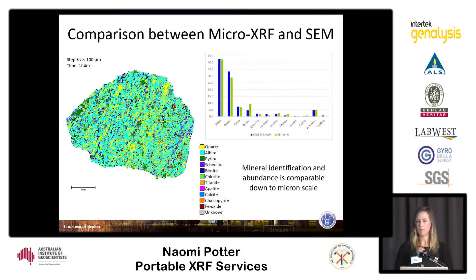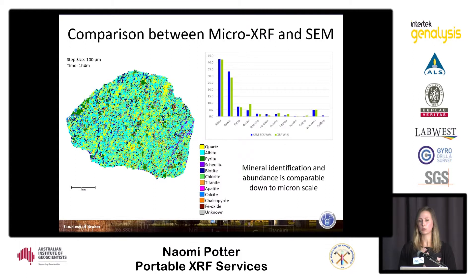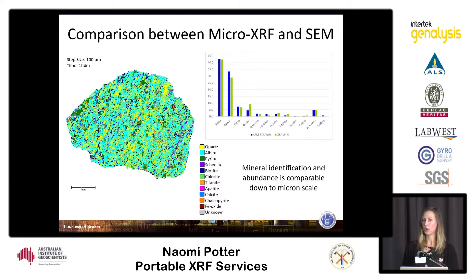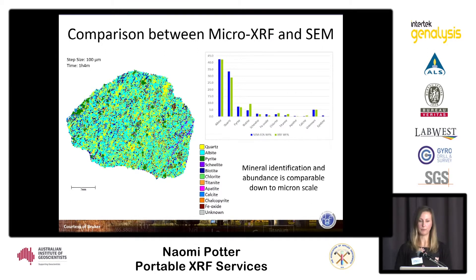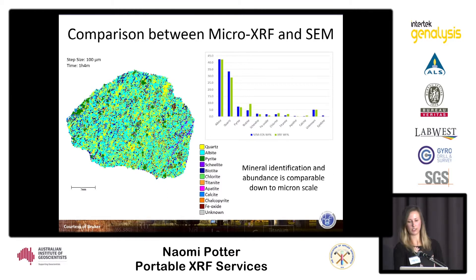The next example was a comparison between micro XRF and SEM, with the same samples analyzed using both methods — and they produced comparable results. The micro XRF slightly underestimated the amount of quartz and overestimated the amount of biotite, but considering the additional cost and complexity of SEM analyses, micro XRF could be quite beneficial for this type of analysis. Micro XRF can also analyze larger samples, though at a lower resolution than typical SEM. This sample was measured at a 100 micron step size, which is why the image on the left is quite grainy, but you can still see the textural features and mineral associations.